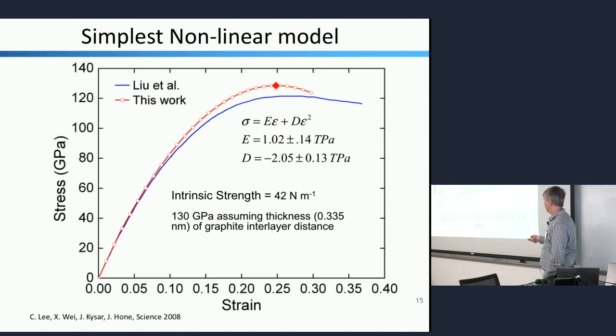It's linear at low strain, as you would expect, every material should do that, and then curves over with an inverse parabola. The Young's modulus, again, is about 1 terapascal. This was about negative 2 terapascals in the bulk equivalent. But the important thing is the intrinsic strength, which you just read off from this maximum value of about 130 gigapascals, which turns into 42 newtons per meter. This is our original value, and this is the value that gets most often quoted. It's close, but it's not exactly right, and I'll talk about why in a couple slides.